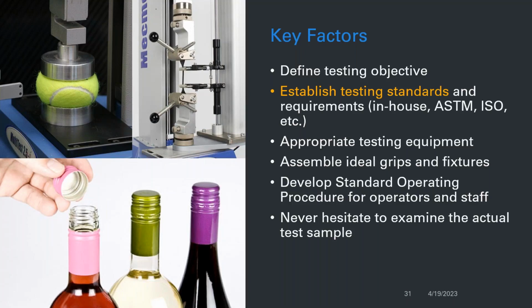So come to find out, just in the process of bottling and capping, anytime there was any splashing or spillage and some of the product went into the threads of the mason jars, it was creating sugar crystallization, which was further applying certain tightness to the caps and just making it impossible to open. So it wasn't just a regular cap on a simple glass jar, but there were additional factors. So those are some of the instances where after you've checked off every single box, you go back and look at the product. And in this case, we were able to identify the crystallization of the sugar that was making it even tighter and impossible to get those caps open.